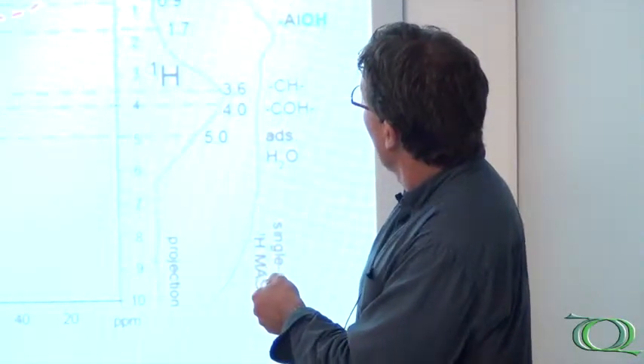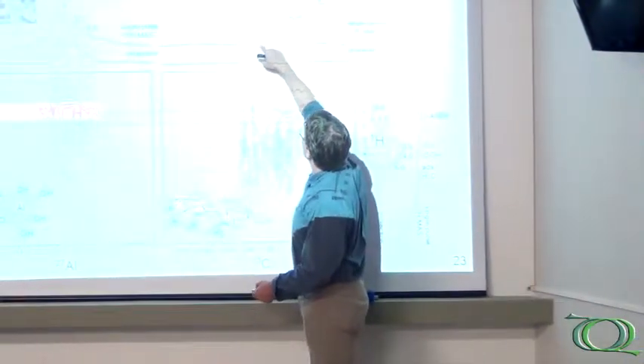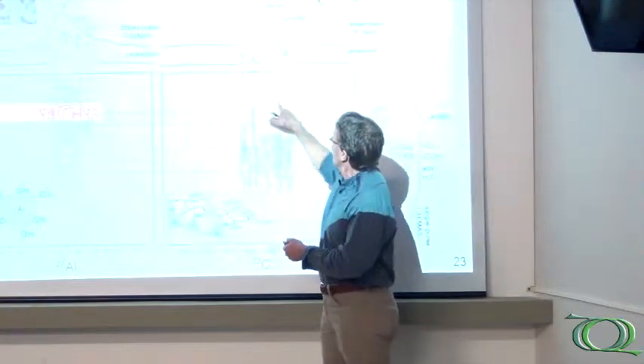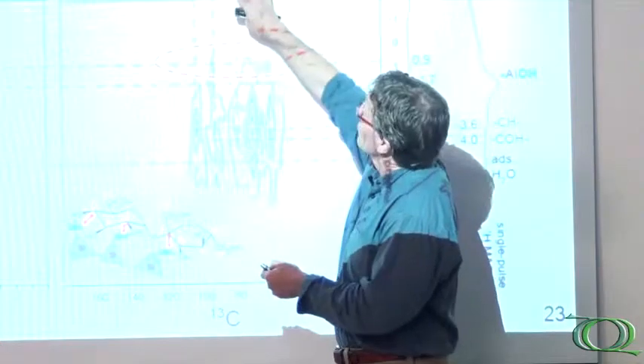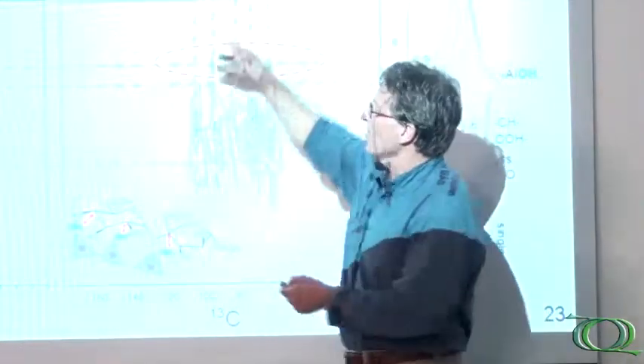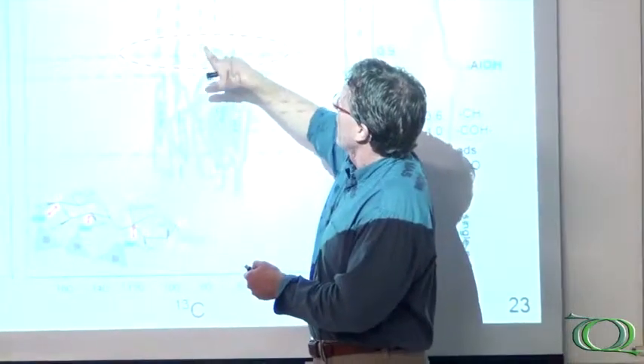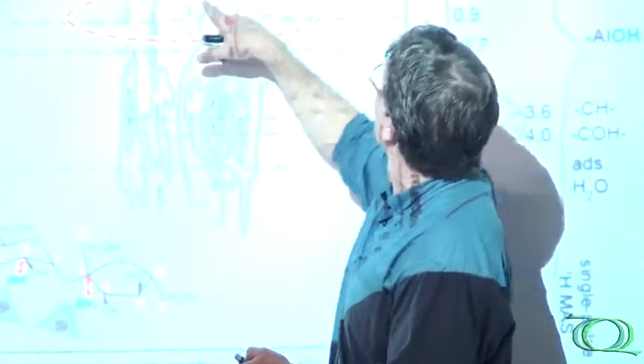So we correlate the proton spectrum with the aluminum spectrum. We also correlate the proton spectrum with the carbon-13 spectrum of sucrose. And in the case of, we took the trouble here to isotopically enrich, use isotopically labeled carbon-13 enriched, excuse me, sucrose. So all of these different carbon sites, one, two, three, four, and so on, are all present in the sucrose. So this is sucrose absorbing on the surface. And what you can see is that from the aluminum spectrum, there is no adsorption and no formation of, on the aluminate hydrate species. So that, and in fact, we have separate evidence to show that the sucrose selectively absorbs on silicate sites, unlike glucose, which absorbs strongly on sites like this, as well as on silicate sites. So the sucrose has a very special structure.